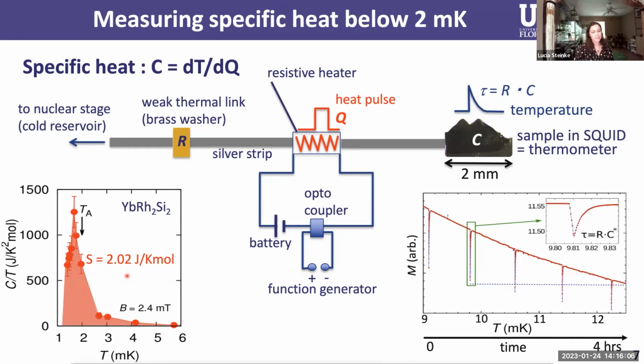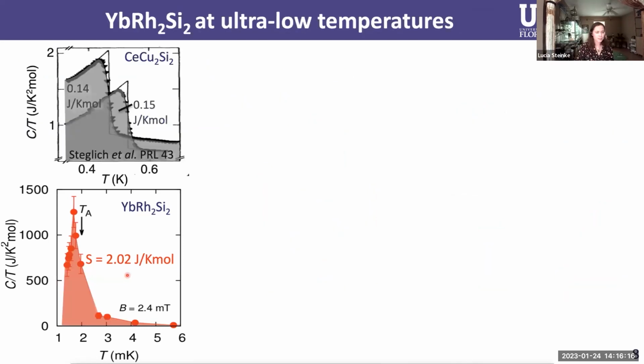So the entropy here is 2.02 joule per Kelvin per mole. To make that a more meaningful number, let's try to benchmark it with something. One benchmark I could think of is comparing it to the superconducting transition in cerium copper two silicon two. And there I looked at the original data published by Frank Steglich in 1979. And you see that the entropy under these two superconducting peaks in two different samples is about 10 times lower than what I measure in ytterbium rhodium two silicon two. So in other words, this specific heat is huge.